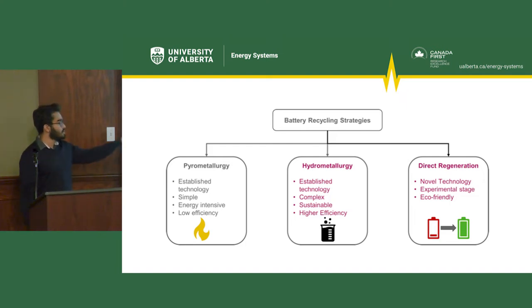Now, these first two methods, pyro and hydrometallurgy, are called destructive methods. Essentially, they destroy the active material while they're doing the metal recovery, and you need to put in a process to bring it back to battery grade. Direct regeneration eliminates that step. Before I explain direct regeneration, one of the reasons why your battery dies is that, as Matt explained, a lithium-ion battery works by lithium shuttling back and forth. And some of the lithium gets stuck while it's shuttling, and the amount of active lithium reduces. So direct regeneration looks to replenish that active lithium using certain techniques, directly regenerating it to be used for a second generation of batteries.